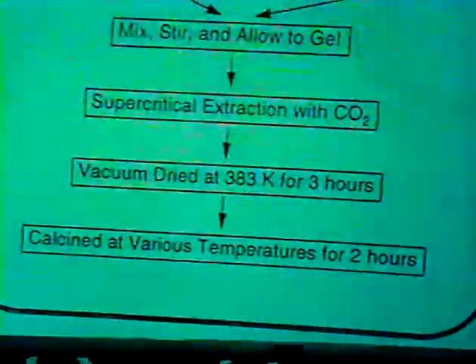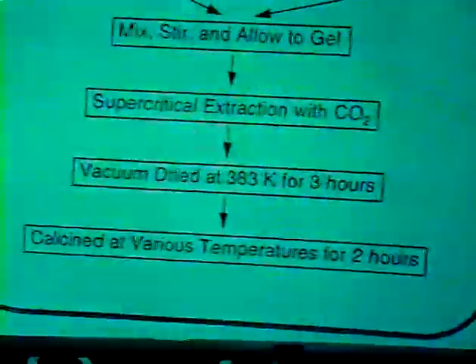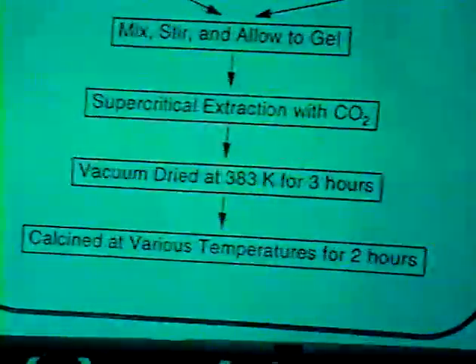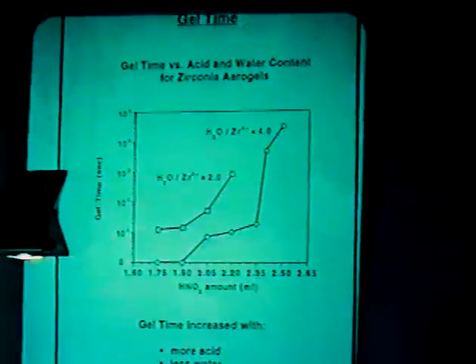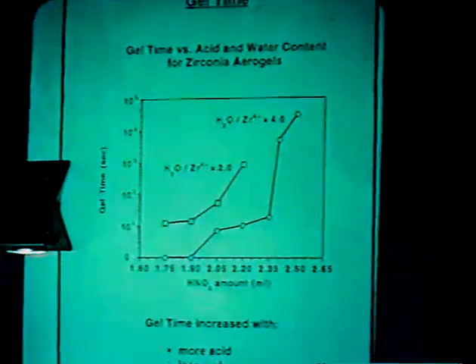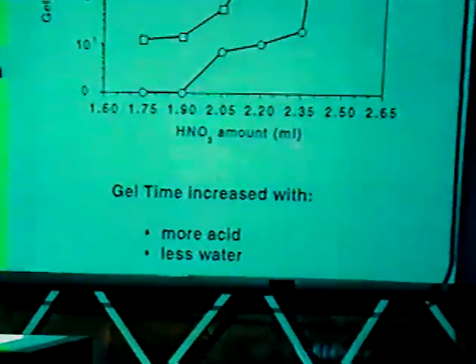After the formation of the gel, we then dry it with supercritical CO2. The material coming out of the extractor was first vacuum dried under these conditions, and then held at various temperatures for 2 hours to convert it into the oxide. Let me show you then the effect of water and nitric acid content on gel time.